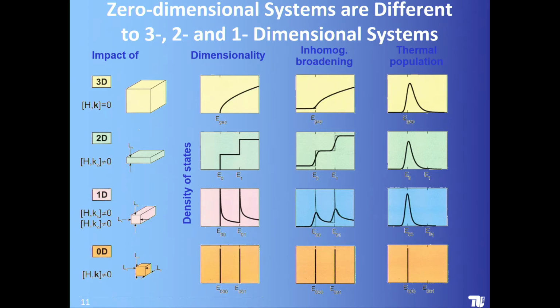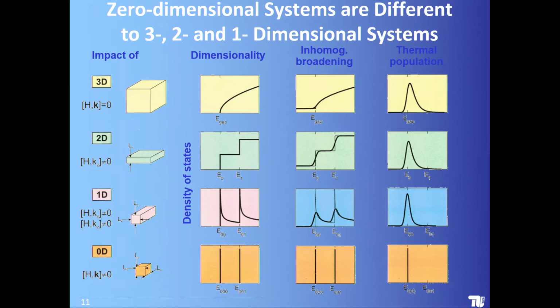Now, in reality, you always have some inhomogeneous broadening in nature, which will influence the density of states, such that, for example, the step function density of states is smoothed out, but it does not influence the quantum dots. Whether the interface between the surrounding matrix and the quantum dots is steep or not doesn't matter, it's a delta function. Now you populate it thermally with carriers, and they look very much the same, except it's getting narrower if you go from 3D to 1D. Here, it's still a delta function, so its emission is delta function-like with a small Lorentzian broadening as a function of the finite lifetime of the charge carriers in the quantum dots.